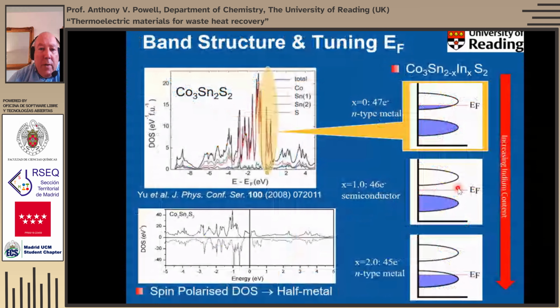And what that means is we have a highly structured density of states, as we can see here. These are some band structure calculations from the literature. Our collaborators at Reading have also done some spin-polarized calculations, which confirm that it is a half metal. But the important point is in the region of the Fermi level, we have two bands, the upper of which is partially filled in the stoichiometric end member. So what we've been looking at is can we lower that Fermi level through this region here of a highly structured density of states and increase the Seebeck coefficient and improve the thermoelectric properties.